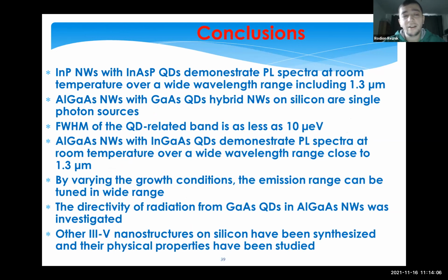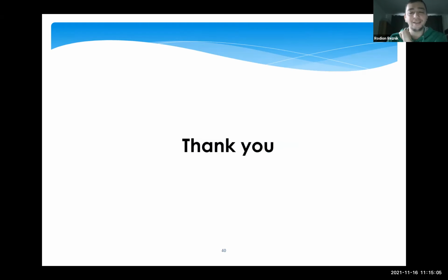So this is my conclusion. I can say that we have grown different quantum dots in nanowires for different applications, like indium phosphide, indium arsenide phosphide system, which is suitable for telecommunication applications, aluminium gallium arsenide material system, which are single photon sources with a high brightness, with a record FWHM of PL peaks of about 10 microelectronvolts, and we have grown different perspective nanosystems based on nanowires with quantum dots on silicon. So thank you very much for listening to me.